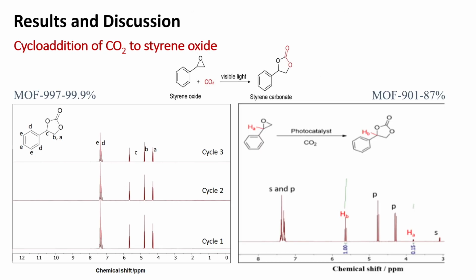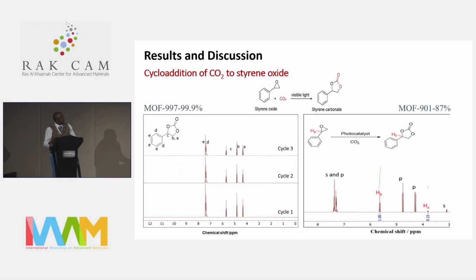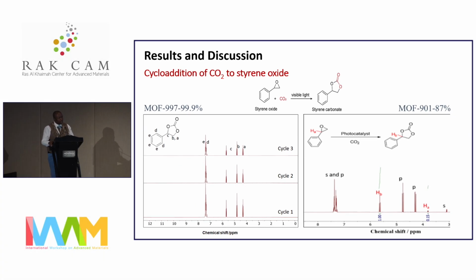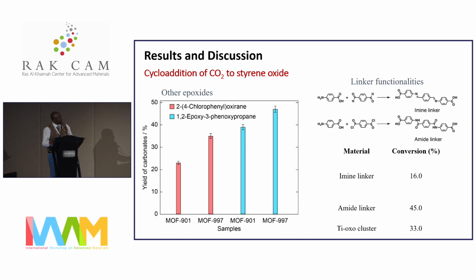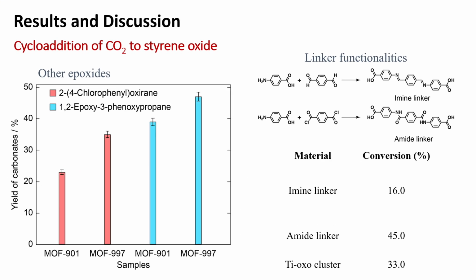So when we applied the MOFs to the cycloaddition of CO2 to the epoxides, we were able to obtain quantitative yields for MOF 997 and slightly lower for MOF 901, therefore showing us that the new MOF material that we had generated was far better in terms of photocatalytic behavior, and could also maintain this performance over a number of cycles. When we applied it to other epoxides, we obtained relatively lower yields but still the same trend. We also tested the linker monomers and obtained a similar trend, where the amide monomers outperformed the Ti-oxo clusters and the imine linker.